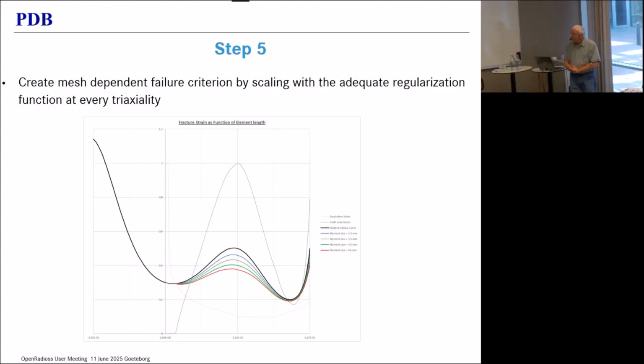And with that, we can now visualize a mesh-dependent failure criterion. The black line is the failure criterion for our initial mesh size, say 1 millimeter, the one for which we validated our material. And then for increasingly large meshes, we reduce by a certain amount for a triaxiality of 1/3 in uniaxial tension. At the intersection point between the instability curve and the failure curve, we stop applying a factor, and our failure criterion is mesh independent. And in between, we have a linear interpolation.